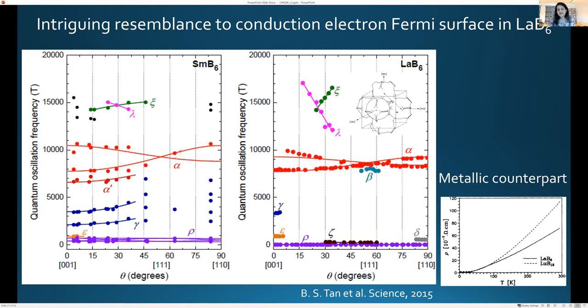Whereas if one were to have a cylinder, a 2D Fermi surface, as you would expect from the surface, when the magnetic field is parallel to the long axis of the cylinder, the area would pretty much go to infinity because there's no intersection. So one would see a cosine-like dependence, with the area shooting up. Basically, you would stop seeing oscillations beyond a certain point, which is not what happens. You see a largely flat angle dependence of the frequency, which is consistent with a more or less isotropic spherical Fermi surface.